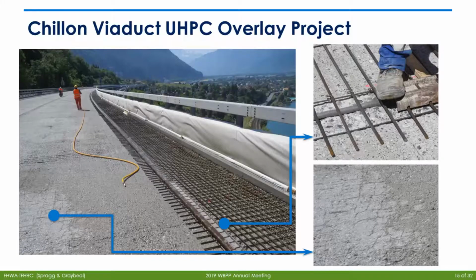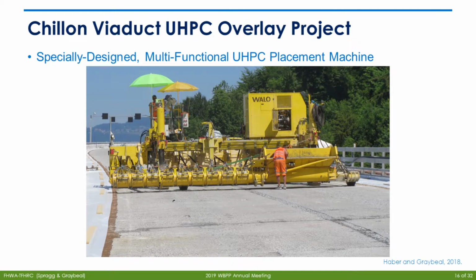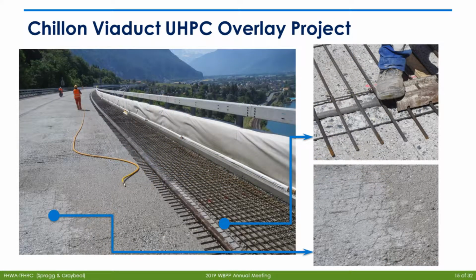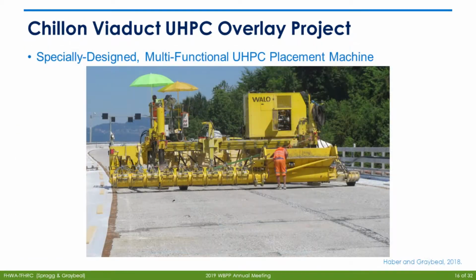So again, you would have the current in-service bridge deck that they hydromilled, and here's an example of how they did the hydromilling. And then where the UHPC overlay was going to be placed. So they did put a reinforcement mat there, and then here are some pictures of what that looked like. Casting the UHPC, they had a special machine that actually brought out the UHPC. They had it in a hopper, they put it in here, and then they placed it with this one lane wide placement machine.